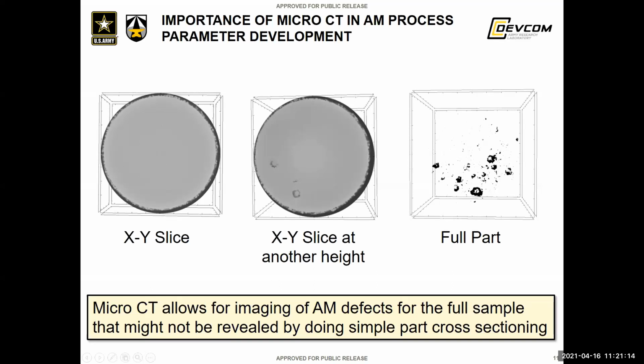However, using CT, we're able to see in the Z direction of the part, and at another slice, there are a couple of defects that are, I'd say, of significant size. And what's interesting with the pulse-based laser is that when you have these types of defects, they're circular around the pulse, so it's a little different than continuous wave, which would be elongated along your melt pool track. And with this, we're able to see the full part and see, oh wow, this has a lot of defects in the Z direction. So this is looking down still X, Y, and this probably would not be a processing parameter we'd want to go through in the future.